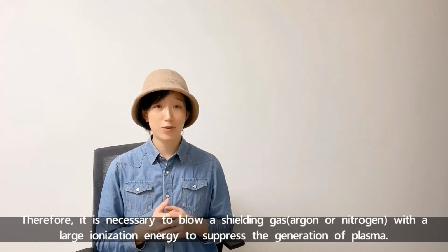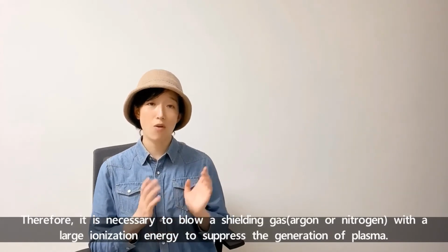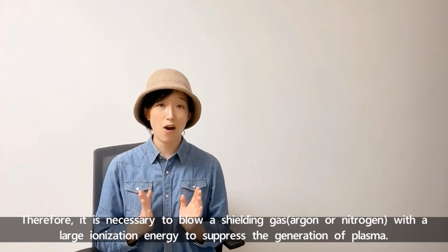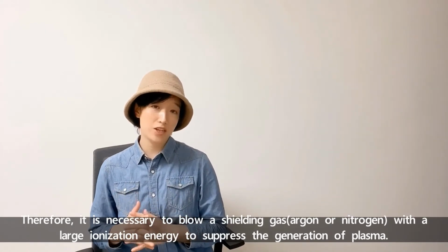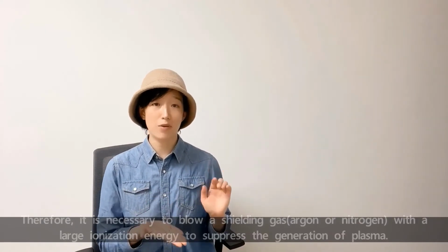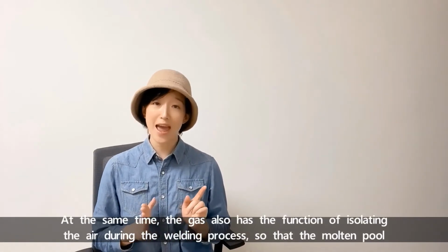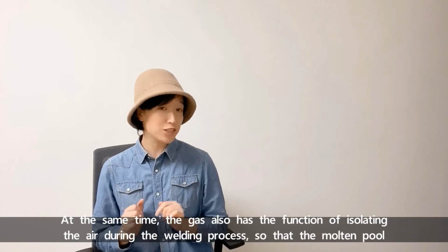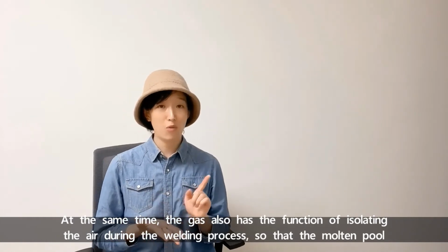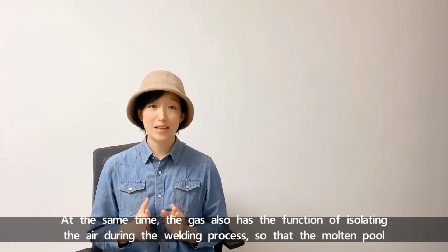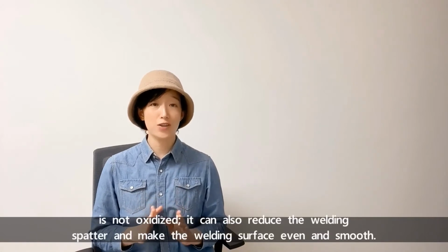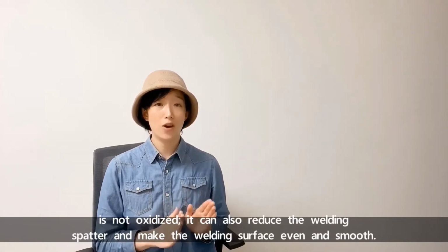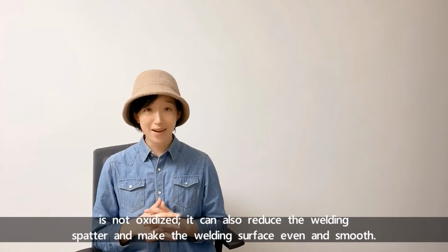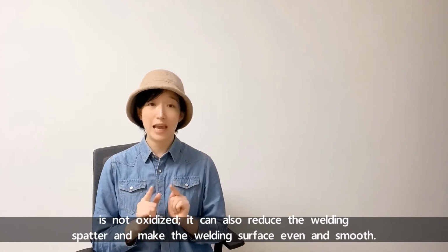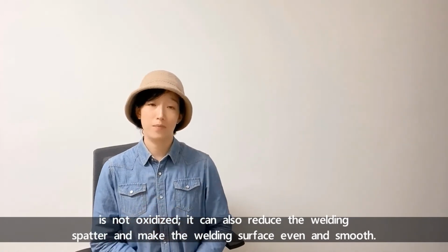Therefore, it's necessary to blow a gas, argon or nitrogen, with a large ionization energy to suppress the generation of the plasma. At the same time, the gas also has the function of isolating the air during the welding process so that the molten pool is not oxidized. It can also reduce the welding spatter and make the welding surface even and smoother.